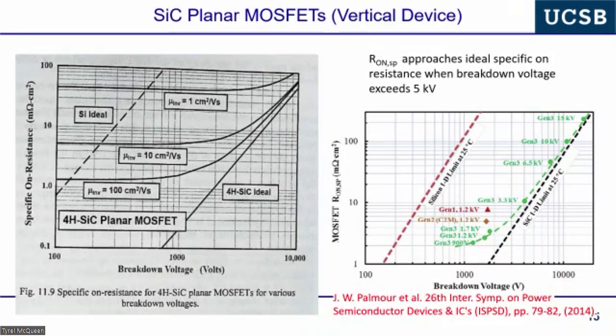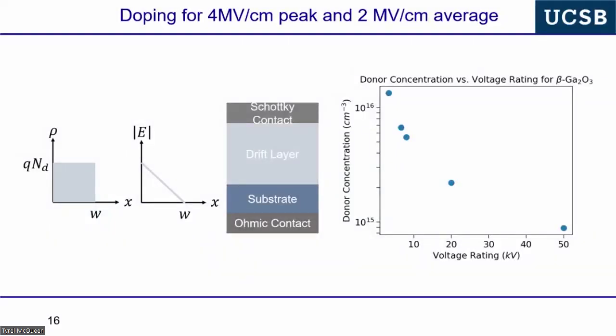Okay, and just to show you where we need to get in gallium oxide for voltages, because we really believe it's in the 10 plus kV regime in our semiconductor, beta gallium oxide, that we can start outperforming any other semiconductor. And that means that we need to have controlled doping, okay, in the low to mid 10 to the 15ths. And this has to be intentionally controlled doping in this range. So this is on the order of 10 to 100 parts per billion purity control, okay? And so that's kind of what we're fighting with for purity. And these have to be in extremely thick epitaxial layers.